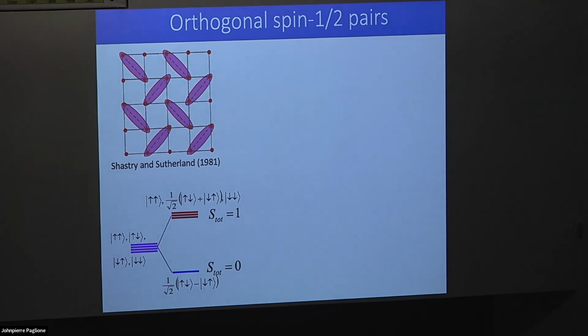And it is a system that has an exact analytical ground state that is known, which is just a product state of singlets. So every single pair of spins which has this strong antiferromagnetic interaction actually forms the singlet state. For copper, the orbital degree of freedom is completely quenched in this kind of material, and so it's just a spin half with a fairly isotropic interaction.